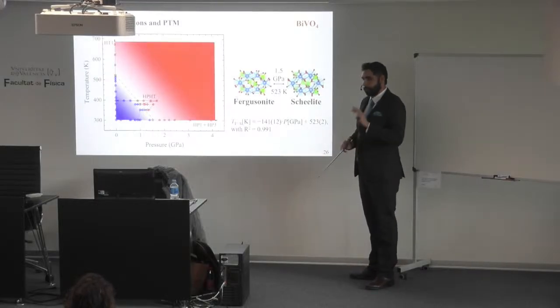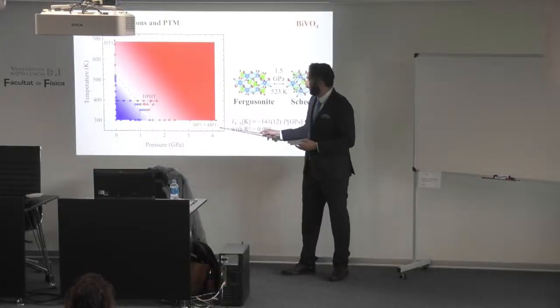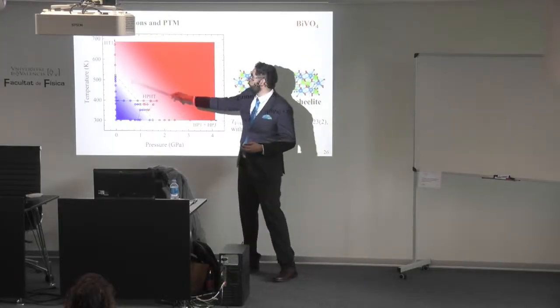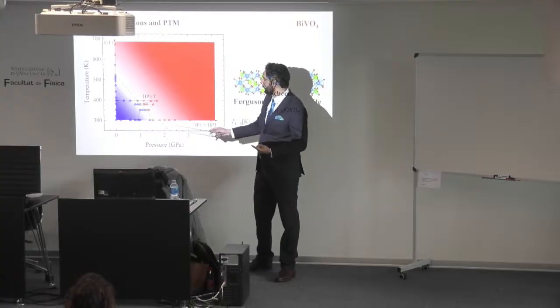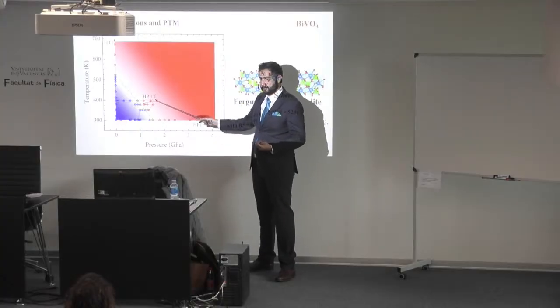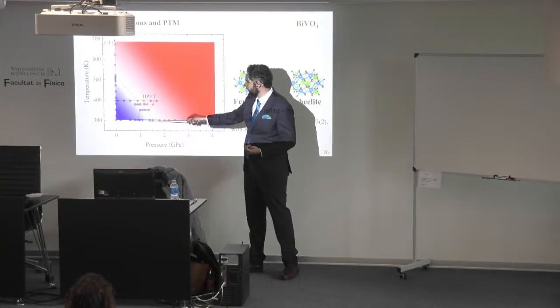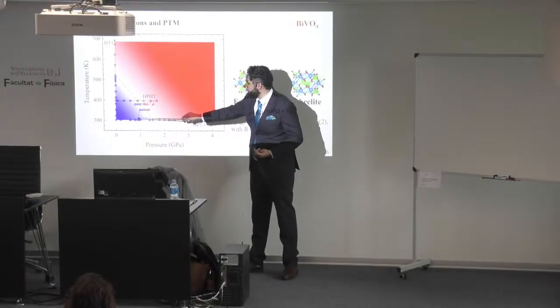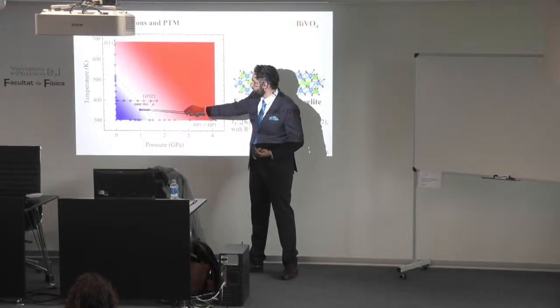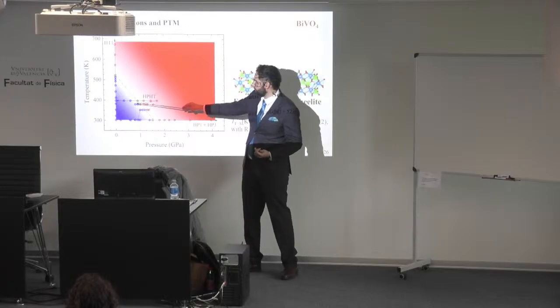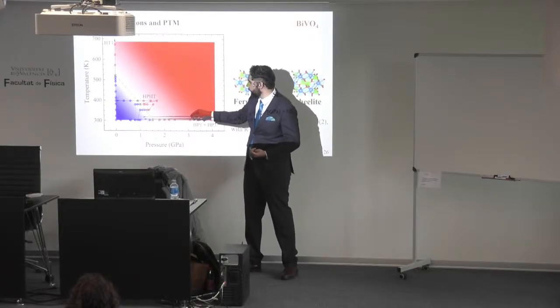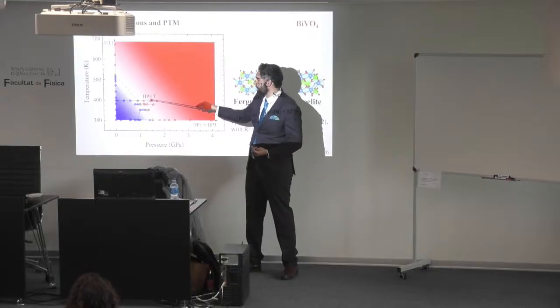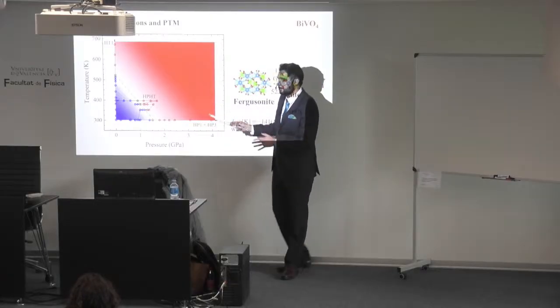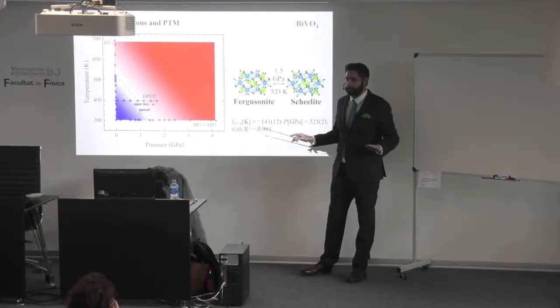We merged 4 experiments in order to build this phase diagram. In this case, a couple of pressure experiments, 1 temperature experiment, and an extra one combining both high pressure and high temperature. So we go up in pressure, then we stop, go up in temperature, stop, pressure, temperature, okay? And we go back and forth in the phase transition.